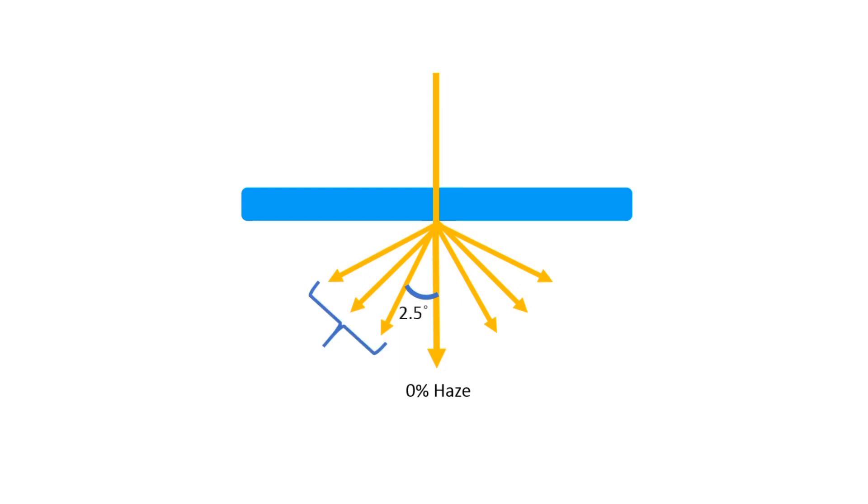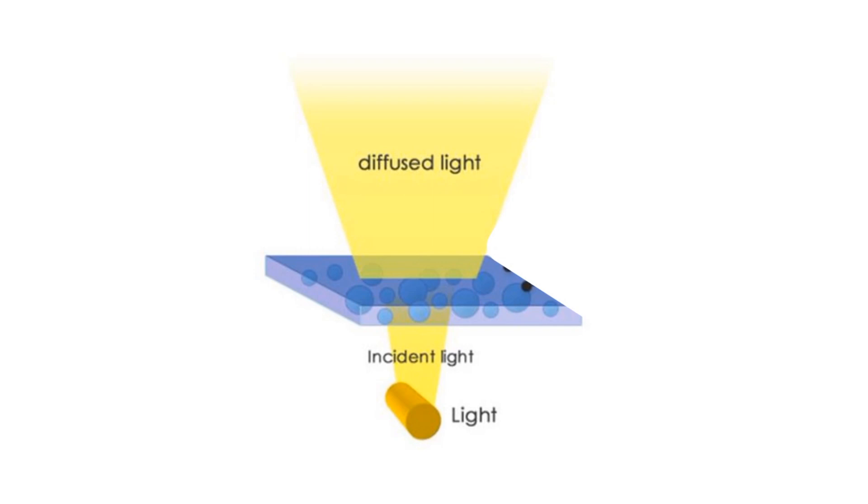The new wood-based aerogel has a visible-range light transmittivity of 97–99%, which is much higher than that of a single clear glass at 92%. It has a haze factor of less than 1%. Haze indicates the percentage of perpendicular incoming light that deflects from the straight line at an angle of more than 2.5 degrees — so if 60% of direct light is deflected, that is expressed as a haze percentage of 60%. A haze of less than 1% is an extraordinary feat, especially when the material is also a very good heat insulator and environmentally sustainable.